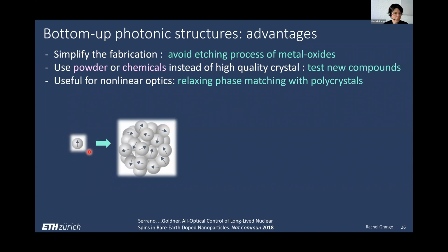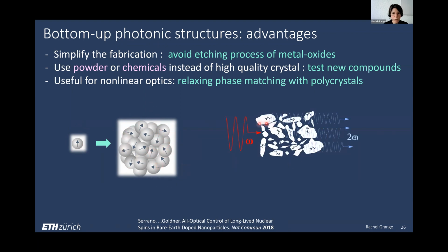If you start from a single crystalline particle of, let's say, barium titanate, what this arrow is showing is the orientation of the crystal axis. We have some ways of fabricating microspheres through templating assemblies, where the orientation of the crystal axis is not at all controlled. And then we end up with microspheres with Chi2 orientations that are totally random.